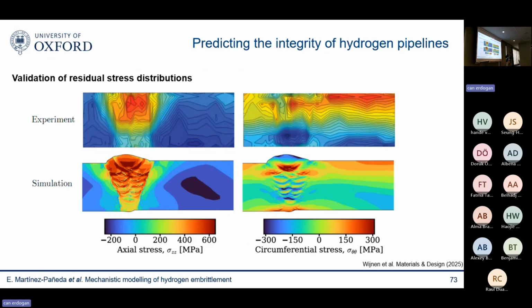We also predicted residual stresses, and again, it's not easy to measure residual stresses, but you can see that this is X-ray diffraction, I think. This is the experiment, this is the model, again, the same legend. And it doesn't look too bad. And we were actually quite happy with the level of agreement. So we are trusting these weld process models that we took from the literature.